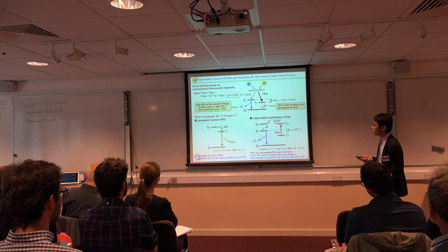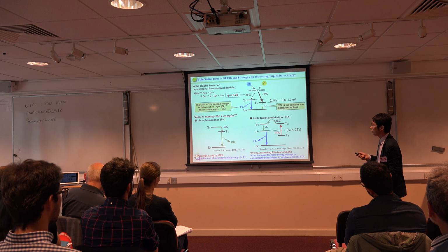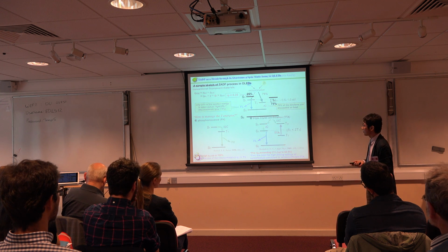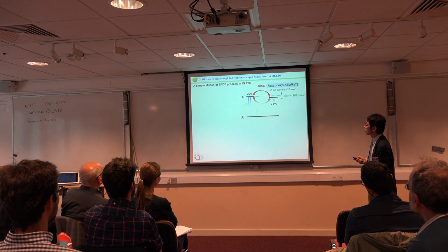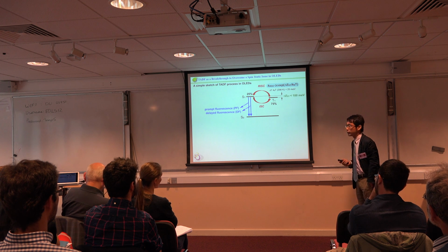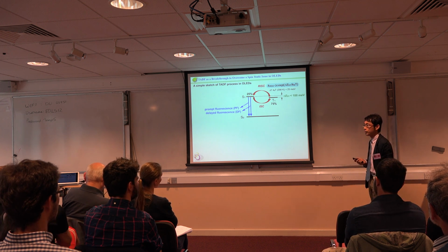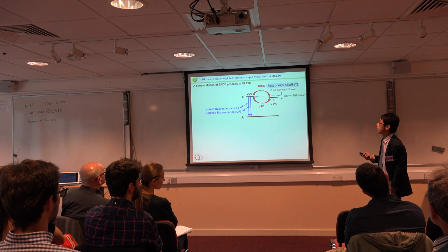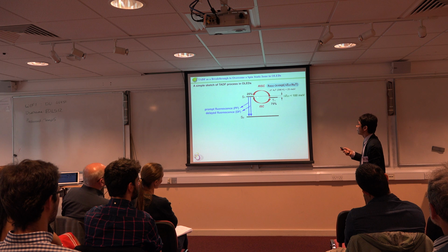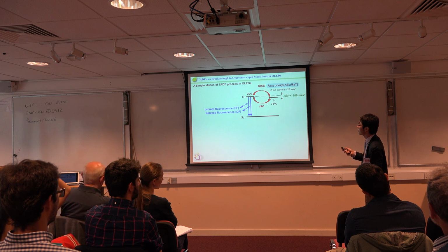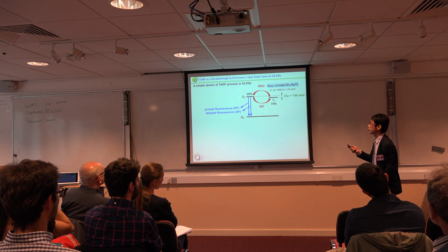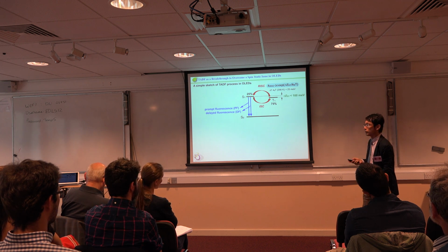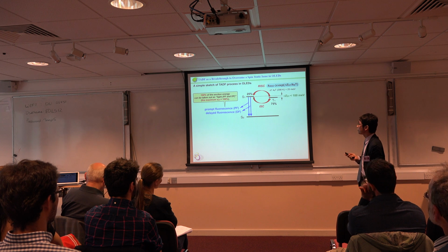To do so, we can utilize phosphorescence or TTA that he also explained, so I can skip. TADF is of course a very efficient strategy for enhancing the quantum efficiency of OLED devices because in principle you can utilize the 75% generated triplet state by converting it to the emissive singlet state, but it's very difficult.